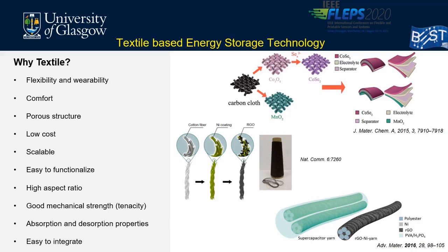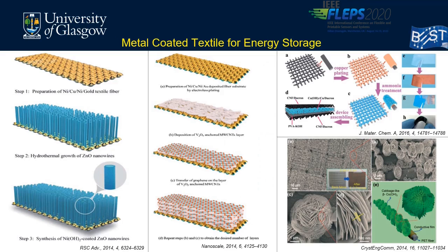Some of the fabric-based or fiber-based supercapacitors that are reported in literature are shown here. In the first one, they use carbon cloth as the substrate material, and in the second and third ones, they use cotton as well as polyester fiber. Then they converted them into a supercapacitive electrode by nickel coating as well as reduced graphene oxide coating as the active electrode material. However, one of the main disadvantages of supercapacitors based on textile is the low conductivity of the textile. So in order to enhance the conductivity, researchers are trying to use metal-coated textile for energy storage application. The high conductivity of the metal will eventually enhance the conductivity of the supercapacitor as well as the capacitance of the devices.